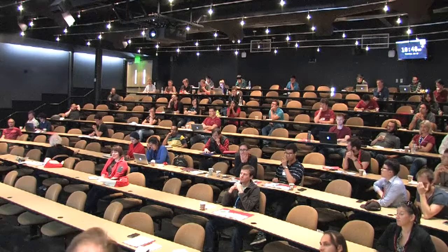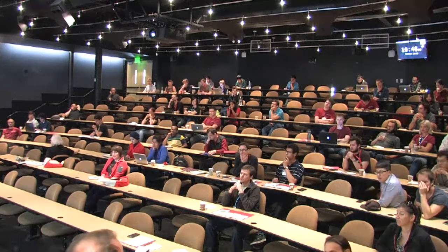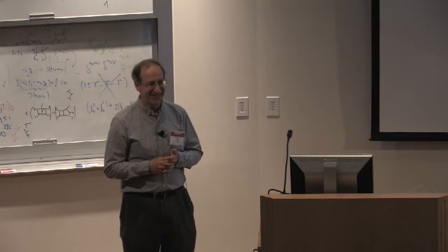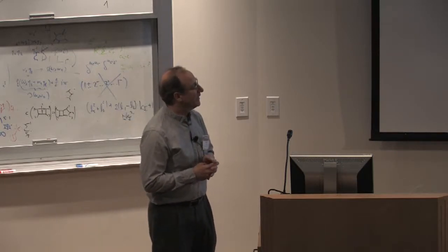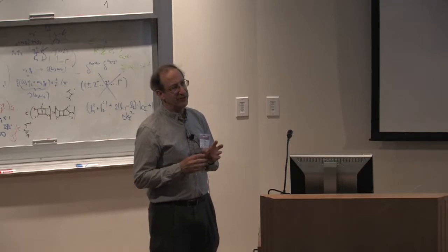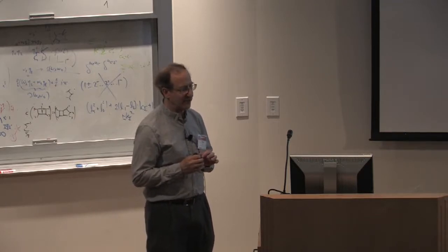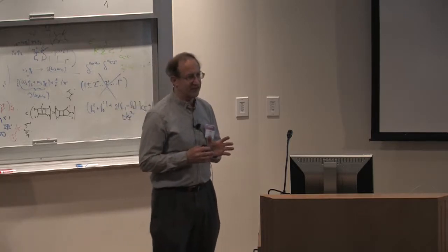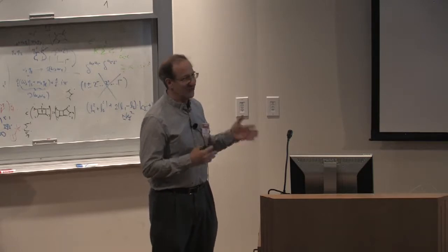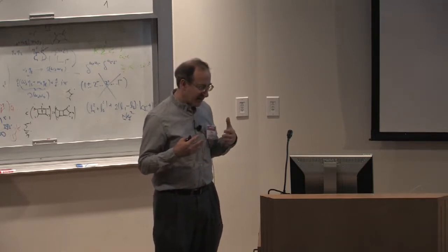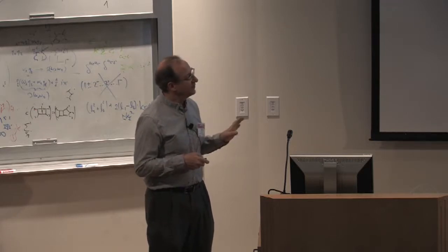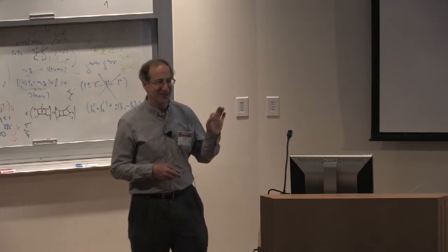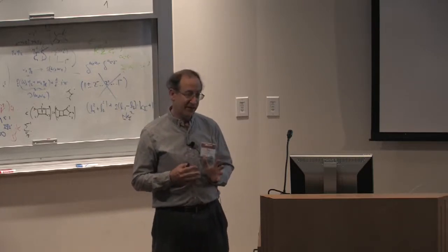Well, damage is always a limitation in these experiments because you have almost an infinite source of X-rays, and even more to come in LCLS-II. If you compare it to the regime of looking at diffraction patterns from very small particles or individual molecules, you actually do have a lot more material here. So you can use lower X-ray fluences than you would in that case. In particular, this somehow looks like the X-ray beam is about one atom wide, but in reality, it was more like a millimeter-sized spot. So it's not highly focused.